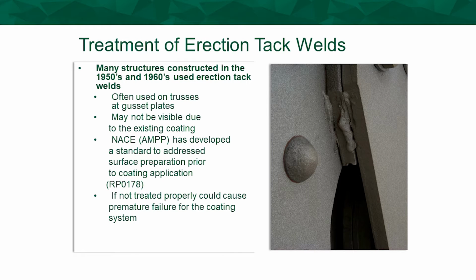Another thing to be concerned about are tack welds. You want to make sure they're cleaned properly, power tooled, smoothed out, because again, going back to the sharp edges, anywhere where you have sharp edges, you could create an issue where paint may flow away from those areas, and now you have accelerated failure or just failing of that system in those areas.